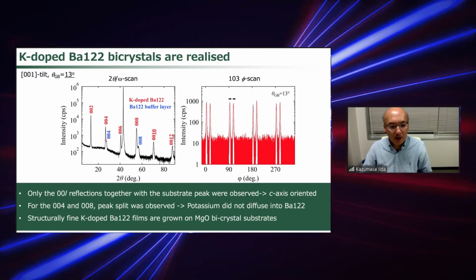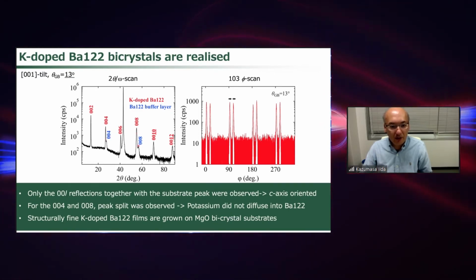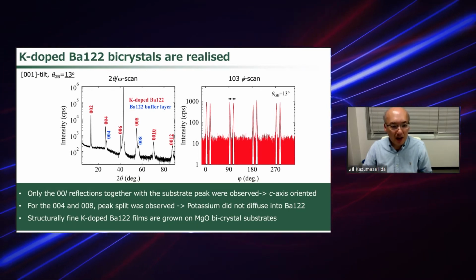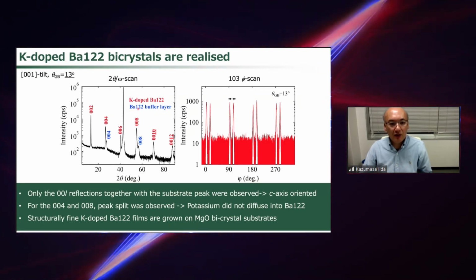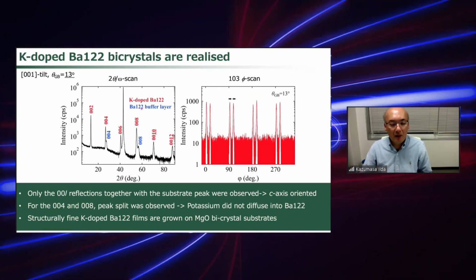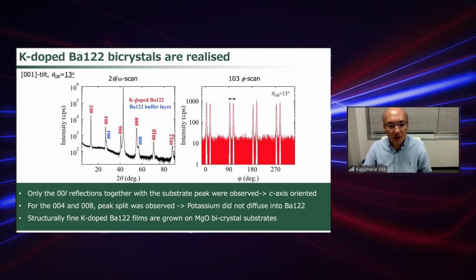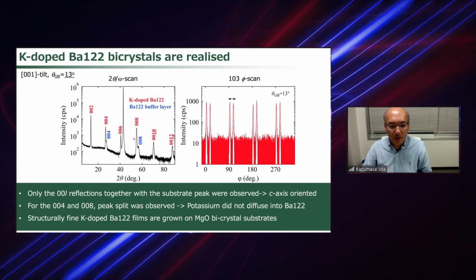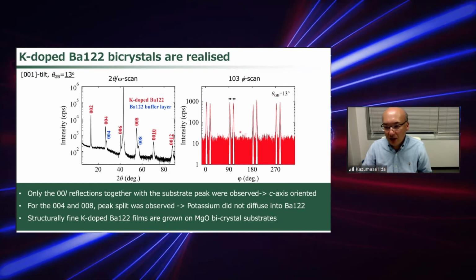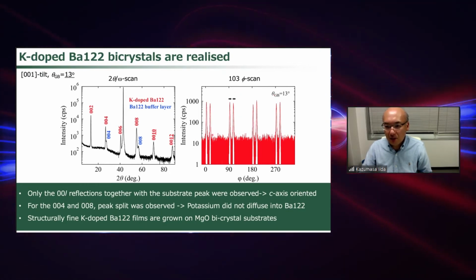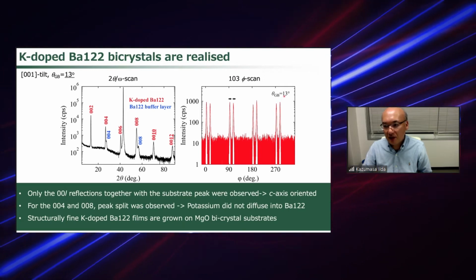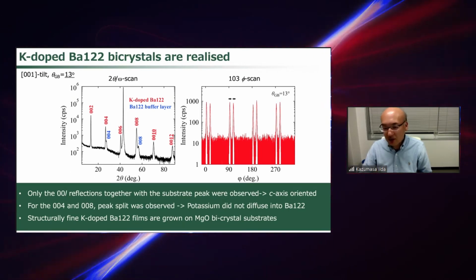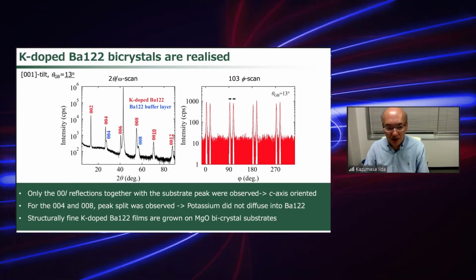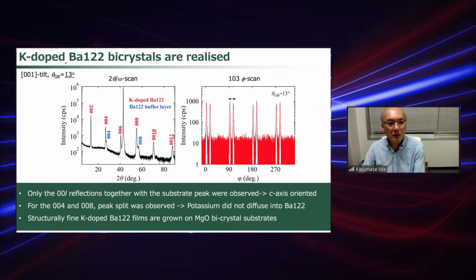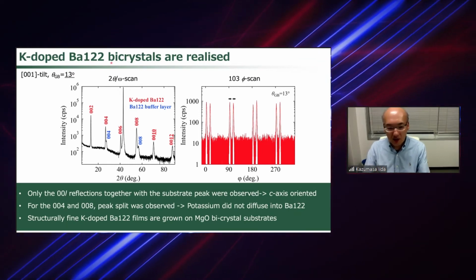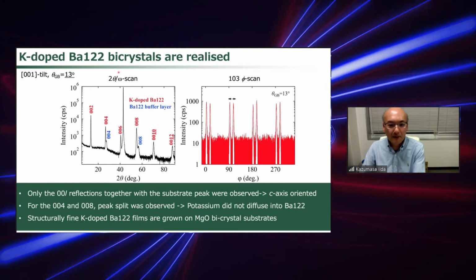But by looking at the 004 and 008 reflections, two peaks arising from the potassium-doped barium 122 and the parent barium 122 buffer layers are observed, which means that the potassium does not diffuse into the parent compound. And here is the 103 phi scan, where two domains separated by 13 degrees, the grain boundary angle, are observed. That means we have successfully grown the potassium-doped barium 122 bicrystals on the barium 122 buffer layers.